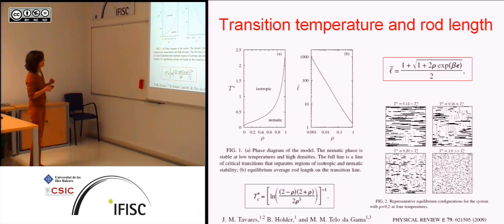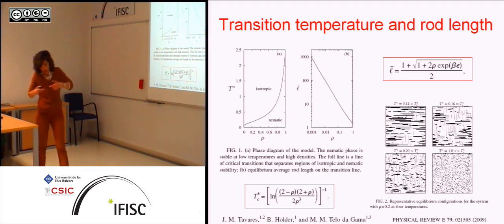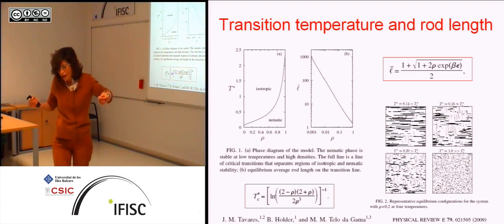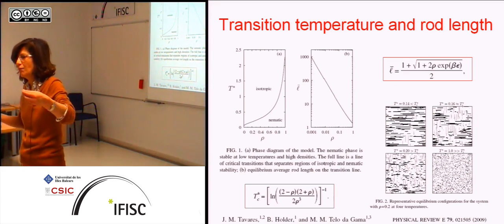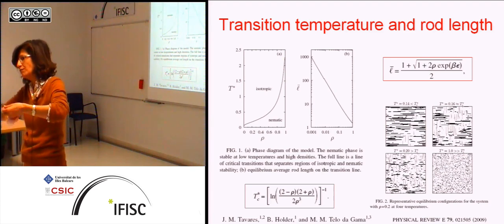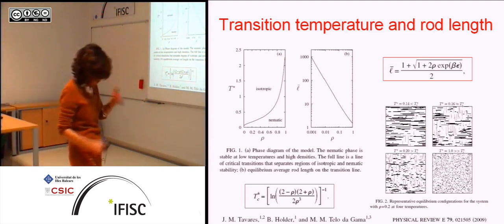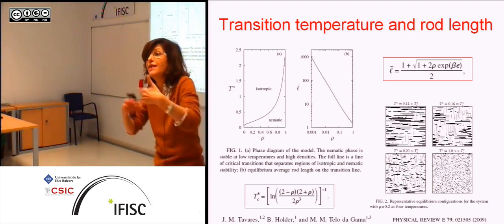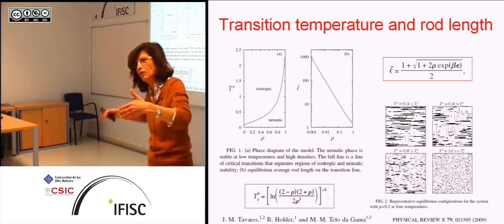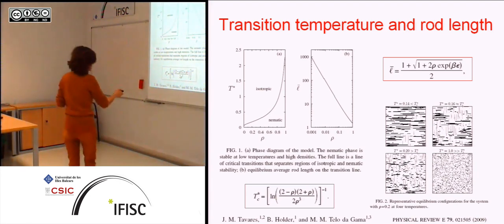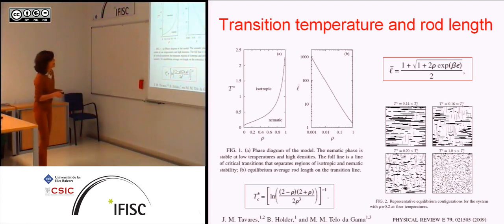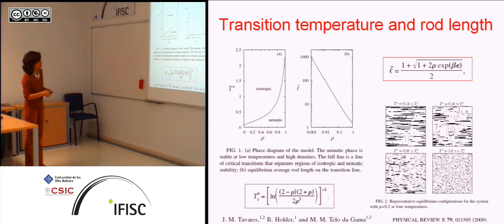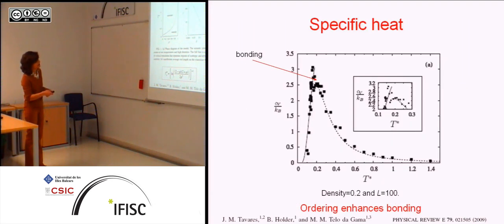And this nematic phase will occur at a given density that is a function of temperature. Now, because the average length of the rods depends also on the temperature, you can imagine that the temperature determines the equilibrium polydispersity. This gives you an average length, and then for a given length there is a density above which the system will phase separate, and will give you this type of ordered domains, okay, nematic domains. This is a simple simulation that we did, and this is below the transition, this is at the transition, this is above the transition, okay?